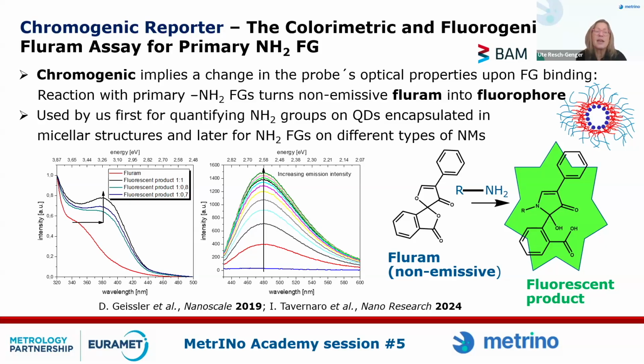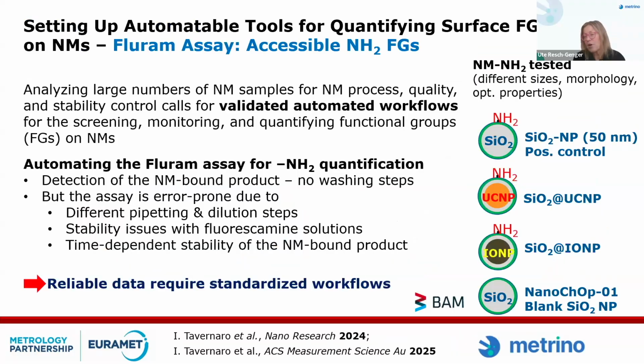So here, when you take a look at the absorption spectrum, the red spectrum is the spectrum of the fluorescamine dye. And when it reacts with amino functionalities, it forms a yellow product, and the emission also starts. The emission has a yellow-greenish touch, and it's quite intense. So you can use this. We used it first for micellar structures and quantum dots, but you can use it for all kinds of nanoparticles.